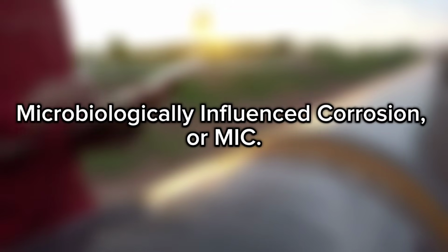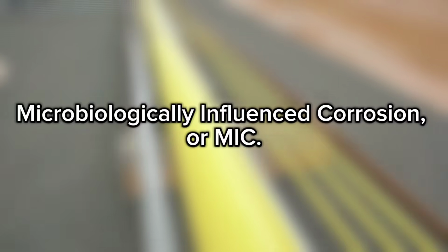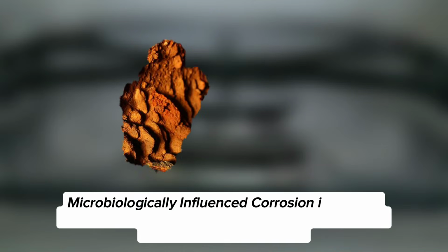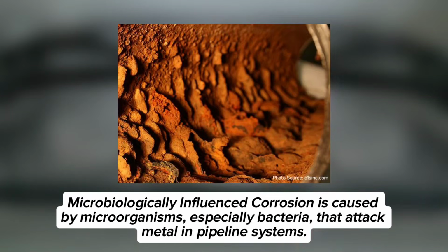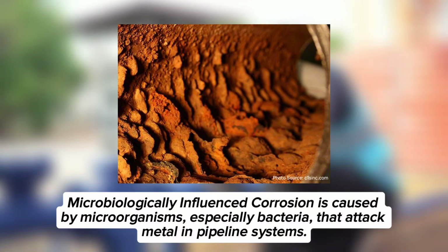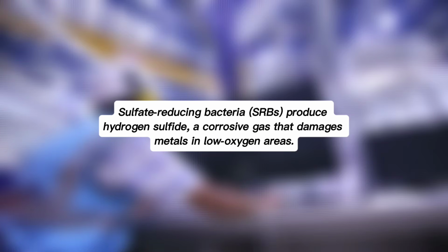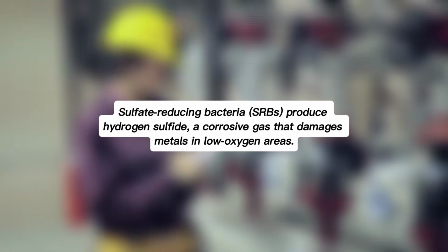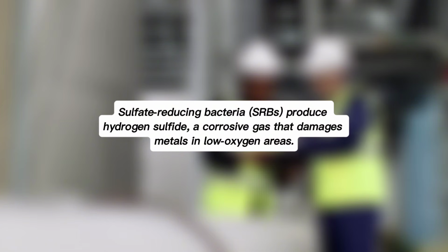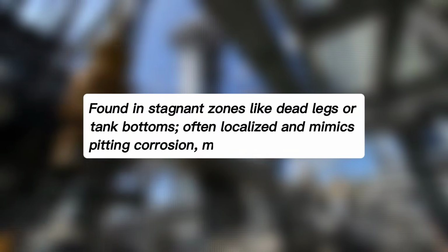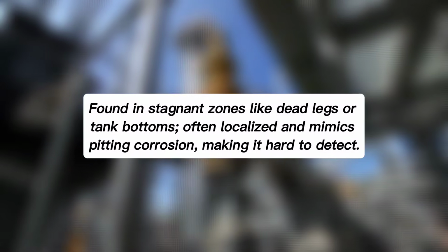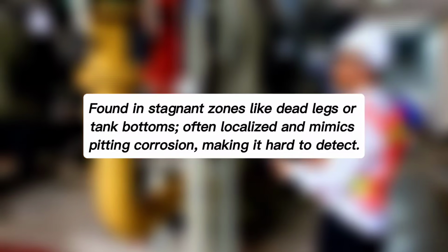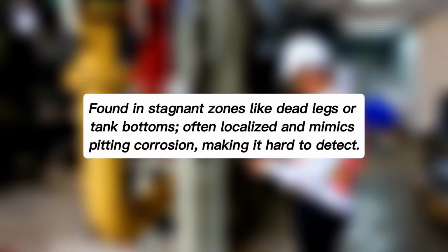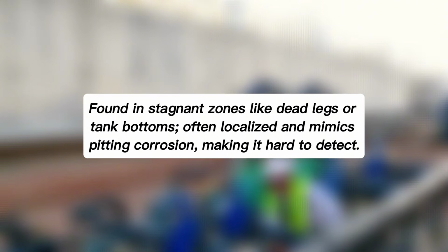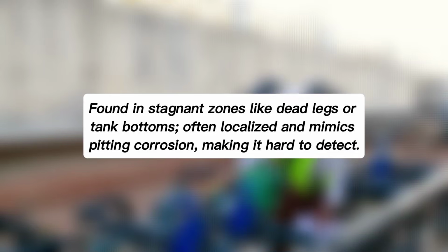Now let's dive into one of the trickiest forms, microbiologically influenced corrosion, or MIC. Unlike chemical corrosion, MIC is driven by microorganisms, especially bacteria, that thrive in pipeline systems. The most notorious culprits: sulfate-reducing bacteria, or SRBs. These microbes live in low-oxygen environments and produce hydrogen sulfide, a corrosive gas that attacks metal surfaces. MIC often shows up in stagnant or low-flow areas like dead legs, water injection lines, or tank bottoms. The corrosion it causes can be localized, aggressive, and difficult to predict. Sometimes it even mimics pitting corrosion, making diagnosis a challenge.